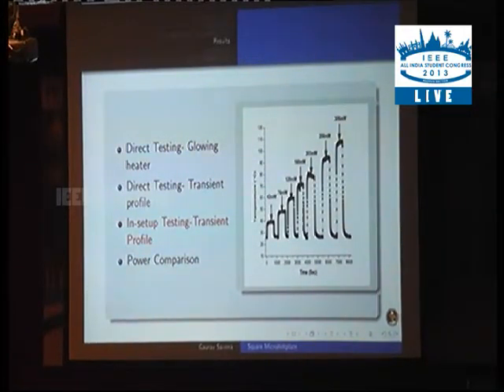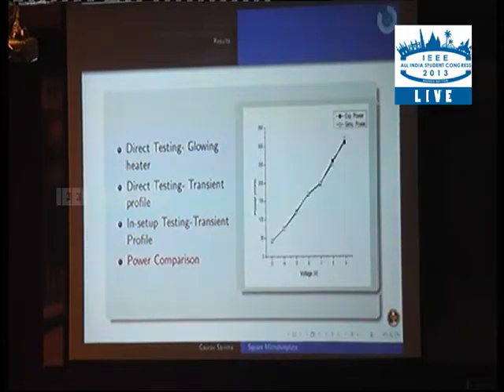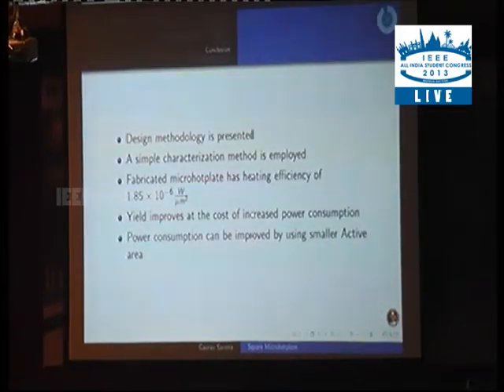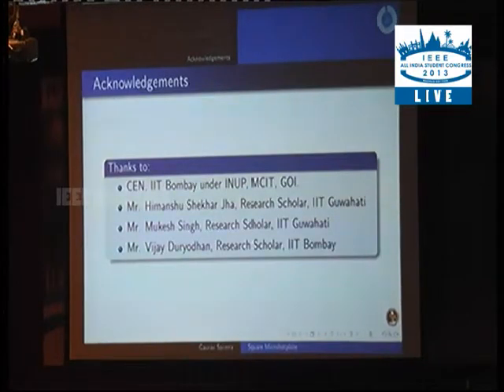It's because it has a high contact resistance and very low current carrying capability. The contacts will burn out if you try to feed more current into it. In the power comparison, we compared the experimentally observed power with the simulated power, and it was in very close agreement. With this, I'd like to conclude and acknowledge my friends in IIT Bombay, IIT Guwahati, and this. Thank you.